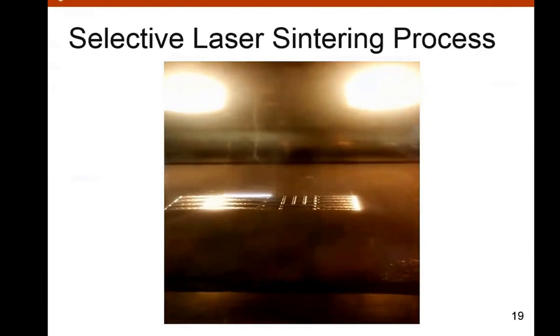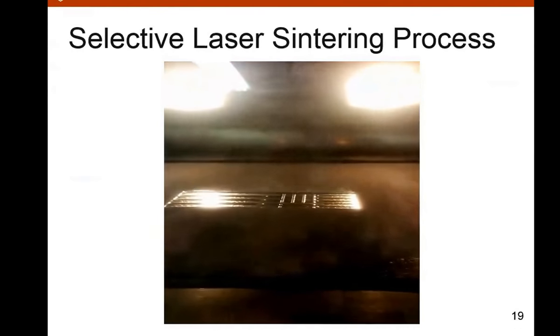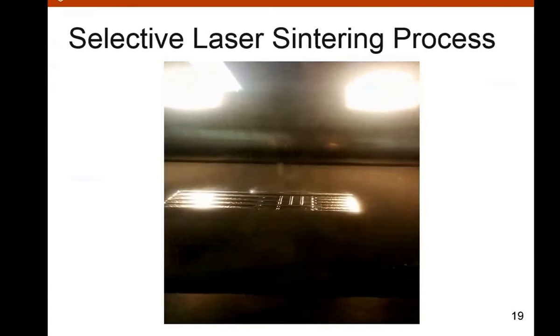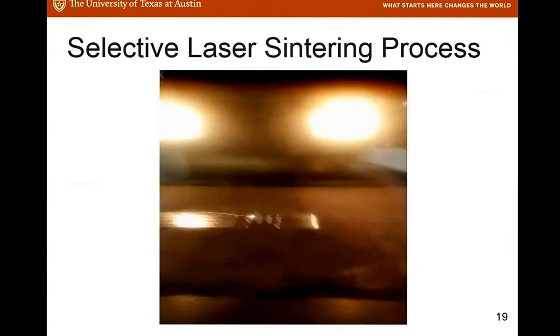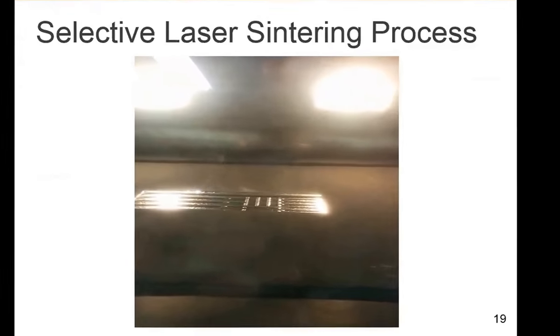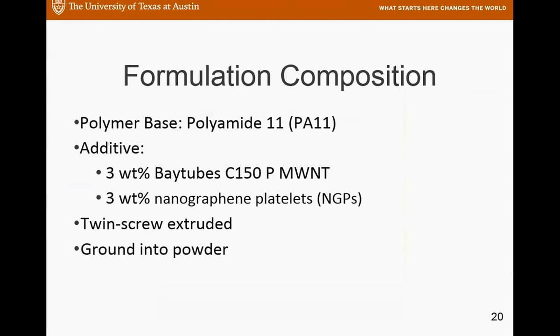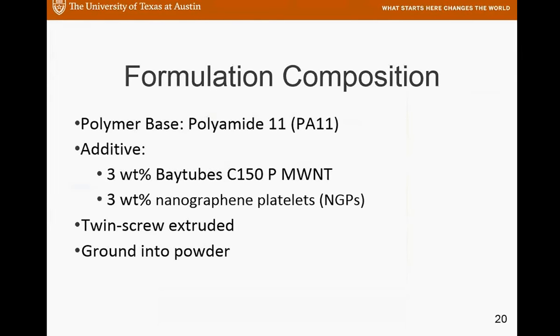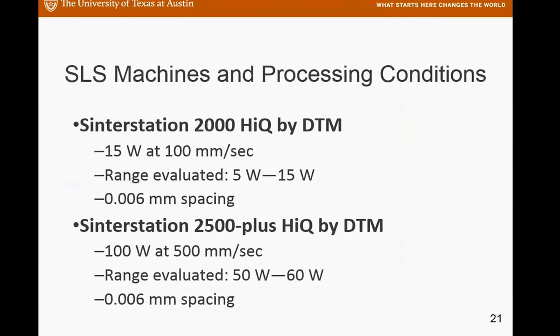And I'm showing you some of these results. This is actually, my student did that. And we were able to use selective laser sintering and print all these test parts in, we have 3 SLS machines in our department. And that's what we were using. But these are very large. We have to come up with over 100 pounds of SLS powder in order to do that. Okay? All right. So we did these formulations. We looked at nylon. We looked at multi-wall carbon nanotube. We also looked at nanographene. We do twin screw extrusion, eventually cryogenically grind these pellets back into powder. So we tried 2 different machines. This is the first one we tried, and the material, actually test samples, are not so good.